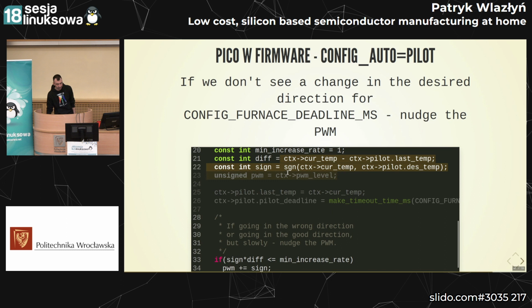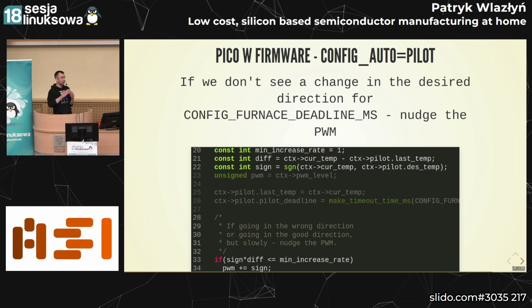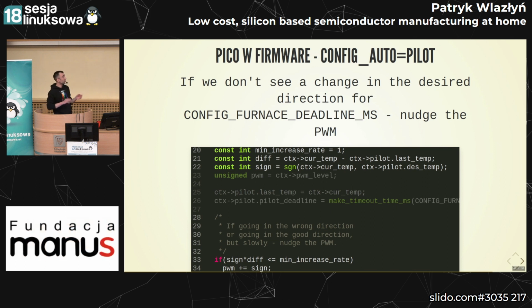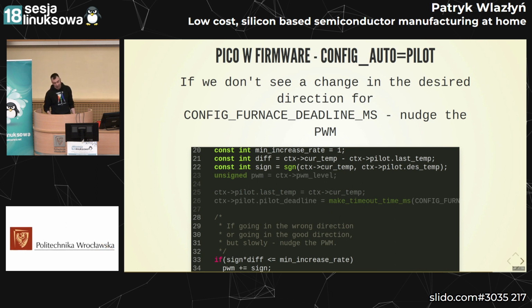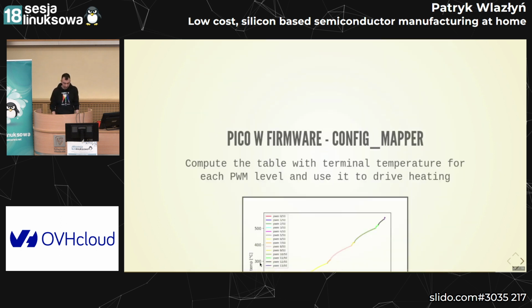So what this code does is basically checking if we are going in the good direction, or going in the wrong direction, or going in a good direction, but very slowly. So let's say right now I have 200 degrees C in the furnace, but I set it to be 600. So I'm checking if we are going in a good direction. If we are going in the wrong direction, or in a good direction but slowly, we just nudge the PWM into the direction we want to go. So if the temperature is too high, we will basically subtract, because we will add a -1 here. It's not that interesting, but I wanted to mention this.